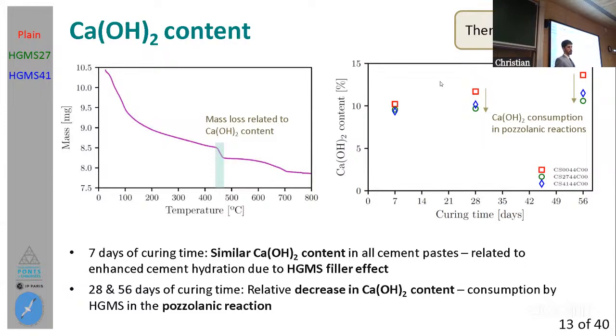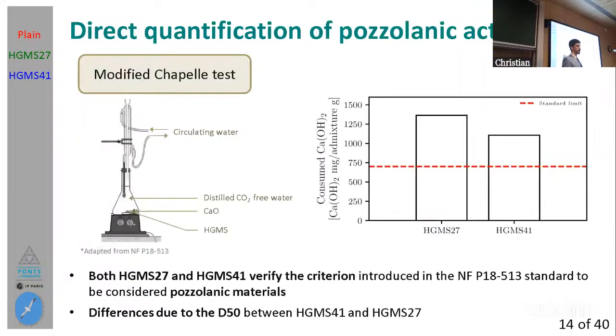First, what you can see there is that we have very similar results in the 7 days calcium hydroxide content, which, given that we have partially replaced cement with spheres, is indicative of the possible filler effect of the spheres, since it's presenting enhanced kinetics of the hydration. If we then take a look at the results at 28 and 56 days, meaning longer curing times, we will see that there is a relative decrease in the content of these hydration products, which could be related to consumption due to the pozzolanic activity of the spheres, which is reacting with the calcium hydroxide to form secondary CSH.